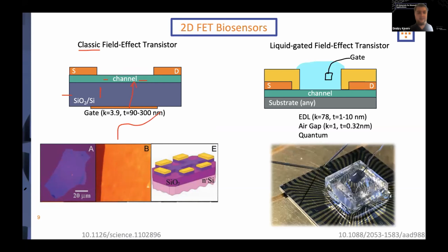In those devices, they will look like literally small pieces of 2D material on silicon. On the other hand, to make really a biosensor, you need this channel to interact well with the liquid most commonly. So you have a liquid, in this case just PBS or water. You have the semiconductive channel. You have a substrate, but the substrate doesn't play any role here. You apply the electrical potential through the electrolyte. And as in any electrolyte, if you apply potential, you form an electrical double layer.